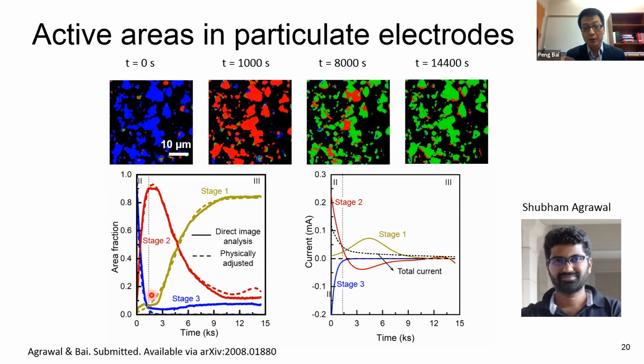Okay, so we have this kind of mutually exclusive sequential process, blue to red, red to gold. And if you just use this image, because each color represents a phase, and a phase means a stable composition, a stable stoichiometric ratio, or mole fraction, of lithium inside, you can actually convert the color into charge. Then if you take a time derivative of the charge, you will get the current carried by each color, or carried by each phase. What's already surprising is that the dashed line is the total current you collected. But looking at the microscopic evolution, the current density is much higher. Or at least it's totally different. So then we went on to do more detailed analysis.